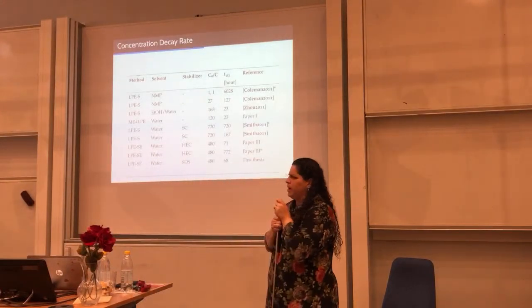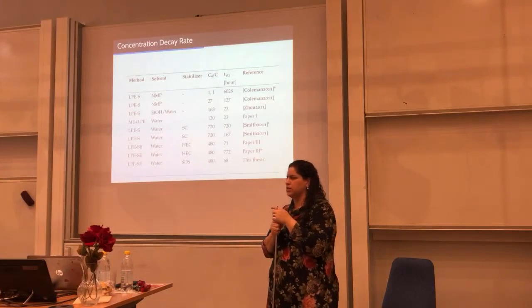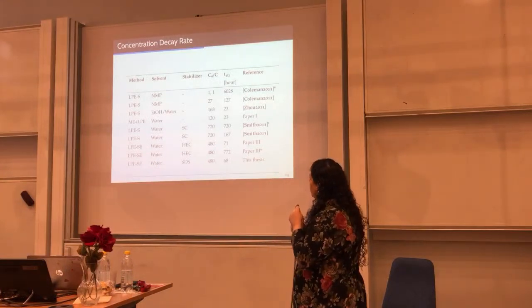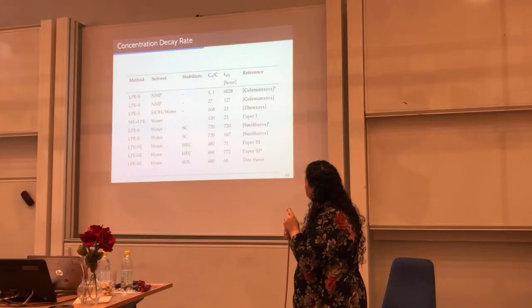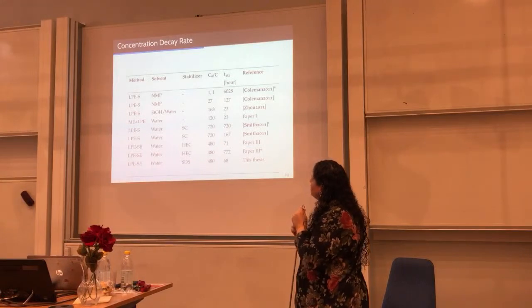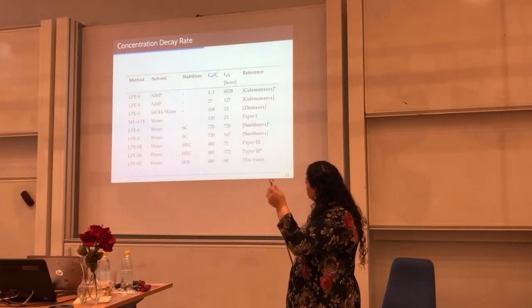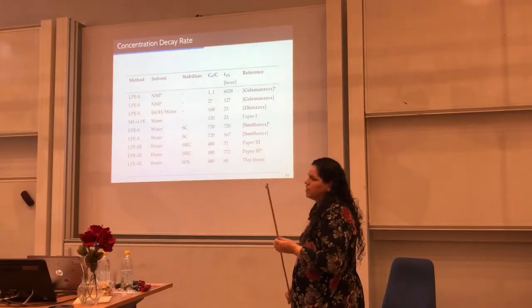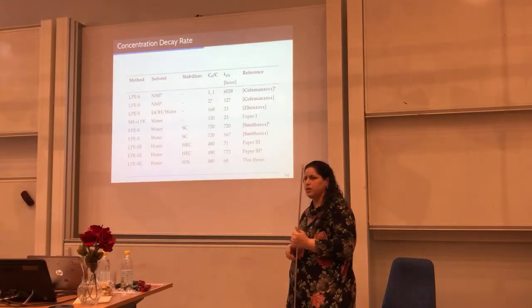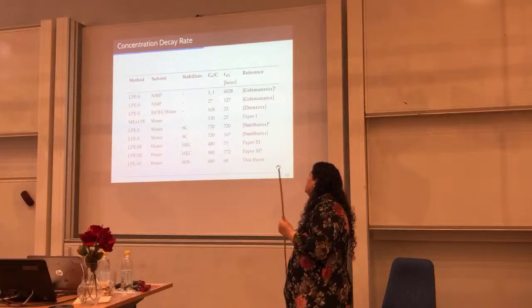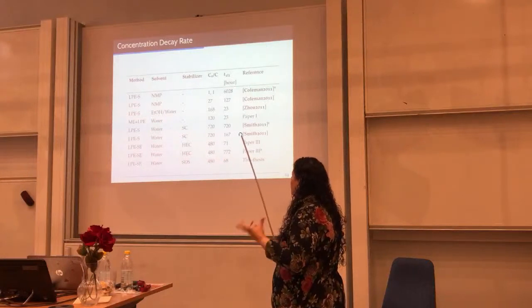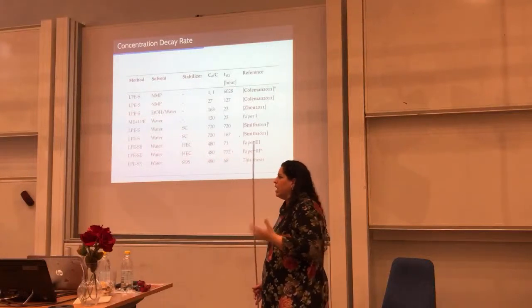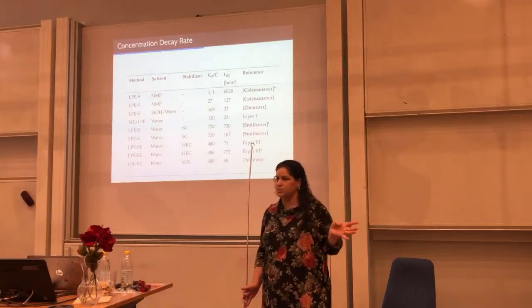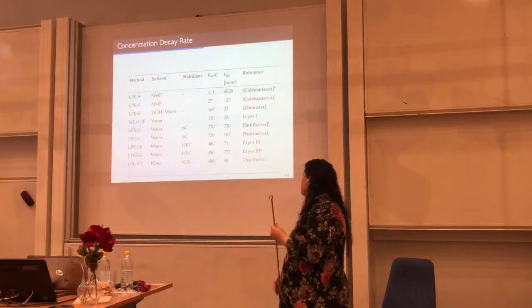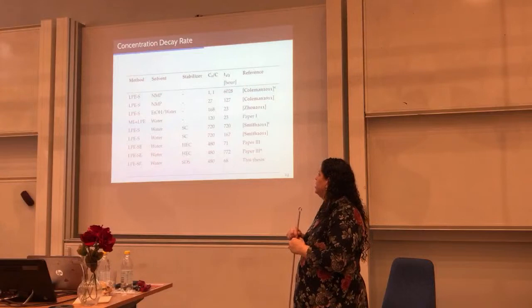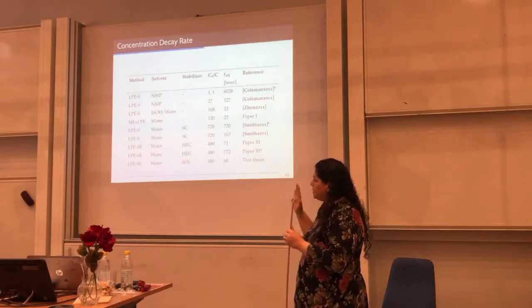So how do we compare our work with the works of others? It's a bit tricky. So Joachim Backstrom gave this idea to measure the concentration decay rate through an equation, a first order reaction equation. So then we can estimate in number of hours when the dispersions of our colleagues in the literature would have the same concentration.